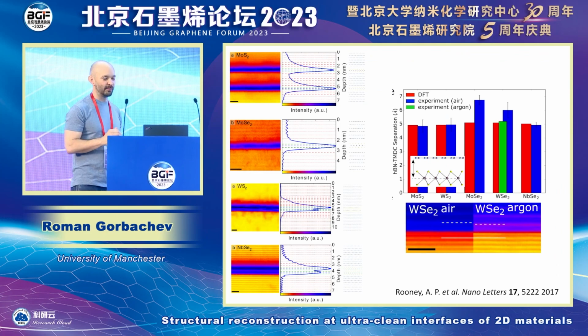So it turns out only about 10 materials are stable in the air, and if you want to explore more, you need to really take care of the environment you're making the samples in. And so doing this in argon allowed us to make a lot more different heterostructures, particularly with TMDs. And you can see here, this is a cross-sectional image. You can see individual atomic planes. And when you stack in argon, you can see that the planes are much closer together because there is no contamination in between pushing them apart, and there is no damage from the air introduced into tungsten diselenide in this case.